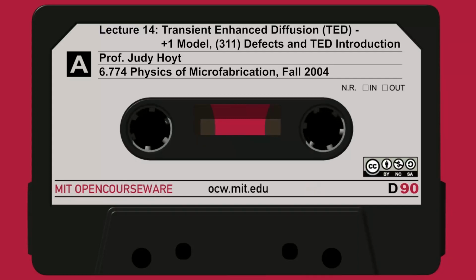Well, the second panel down shows you another idea. How about melt the sample? That's pretty drastic. Hit it with a laser and melt it for a few nanoseconds. So it completely melts, but it melts for so short a time that nothing moves. That's melt-induced laser annealing and regrowth. After you do that, you've melted the sample, you get rid of everything. Then you do the 850 10-second RTA, and lo and behold, all those wings are gone. So the boron stays put.